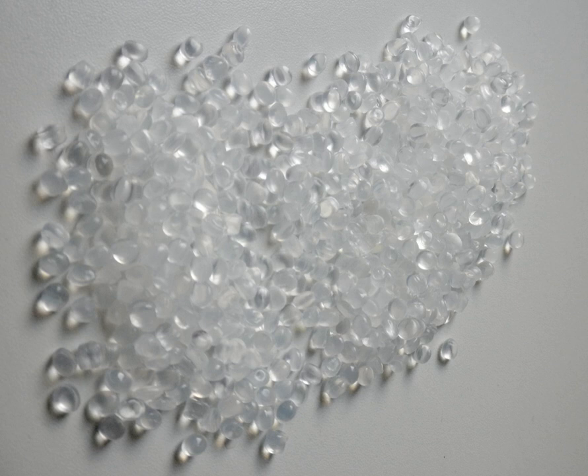Ethylene copolymers with unsaturated esters. If unsaturated esters are copolymerized with ethylene, either the alcohol moiety may be in the polymer backbone, as is the case in ethylene vinyl acetate copolymer, or the acid moiety, e.g., in ethylene ethyl acrylate copolymer. Ethylene vinyl acetate copolymers are prepared similarly to LDPE by high pressure polymerization. The proportion of comonomer has a decisive influence on the behavior of the polymer. The density decreases up to a comonomer share of 10% because of the disturbed crystal formation. With higher proportions, it approaches that of polyvinyl acetate, 1.17 grams per cc.